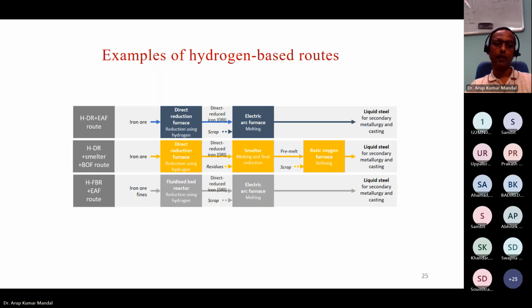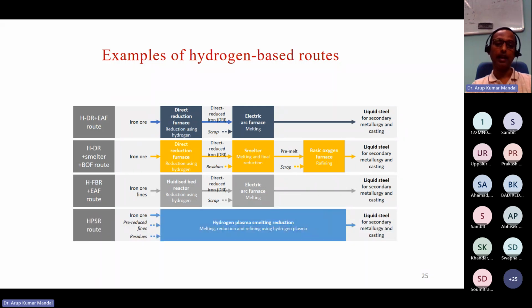And hydrogen-based DRI is very fine in nature. If you produce it in a fluidized bed reactor, then this FBR, hydrogen-based fluidized bed reduced DRI, with the electric arc furnace route, can also produce the liquid steel. And finally, the process I'm going to discuss is hydrogen plasma smelting reduction.